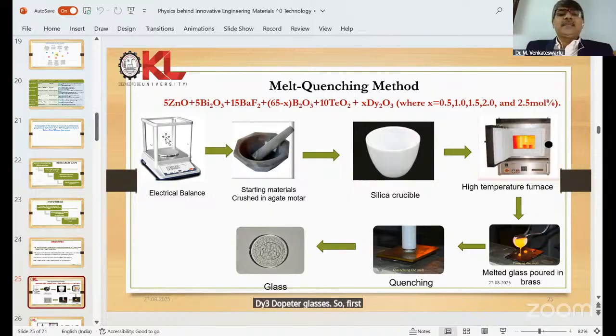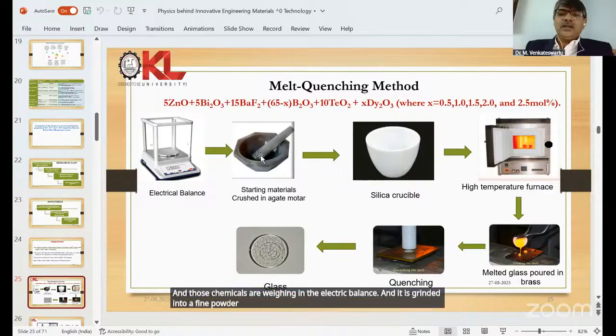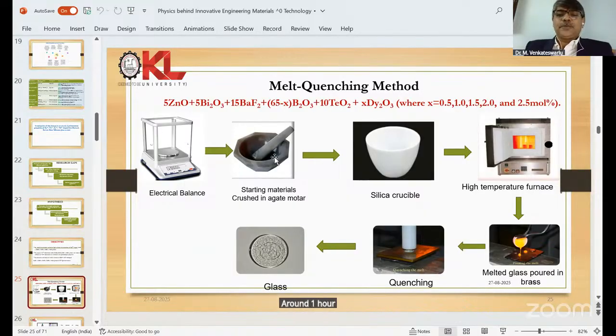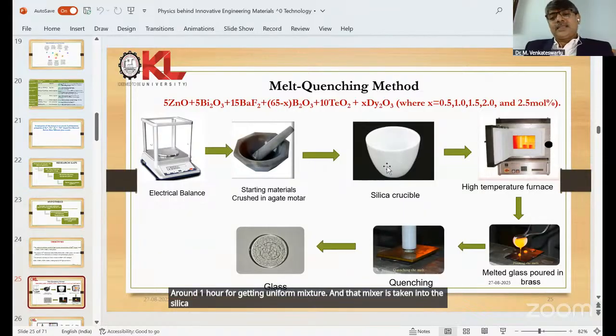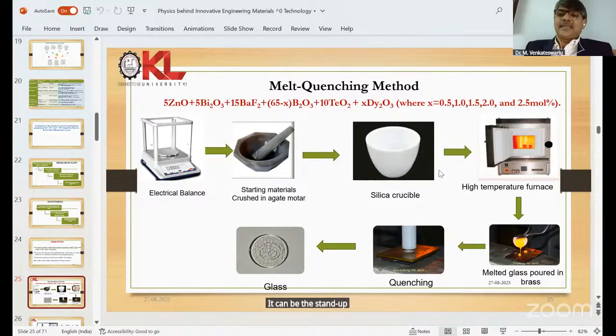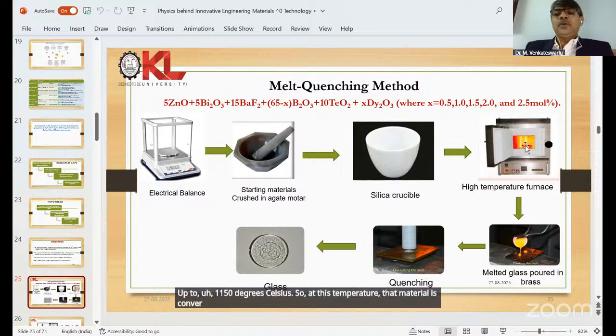First we take the molar percentages, total 100%, and those chemicals are weighed in an electric balance. It is ground into a fine powder in an agate mortar for around 1 hour to get a uniform mixture, and that mixture is taken into a silica crucible. It can stand up to 1200 degrees Celsius temperature. Now this silica crucible is placed in a programmable furnace up to 1150 degrees Celsius. At this temperature, the material is converted into liquid state.